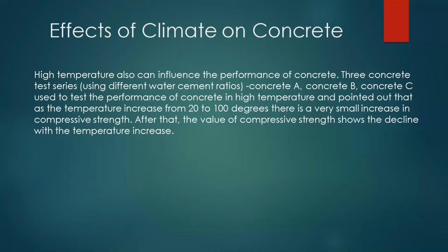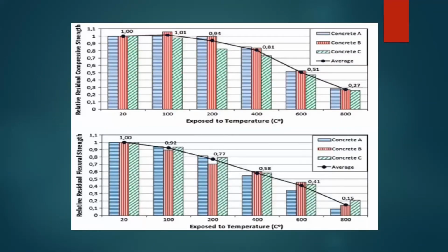High temperature also can influence the performance of concrete. Three concrete test series using different water cement ratios, concrete A, concrete B and concrete C, were used to test the performance of concrete in high temperature, and pointed out that as the temperature increased from 20 to 100 degrees, there is a very small increase in the compressive strength. After that, the value of compressive strength shows the decline with the temperature increases. Here's the figure of the experiment I just told you.